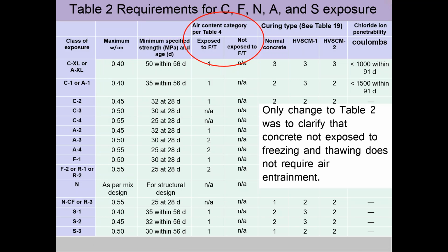Okay. One other change, the only change to Table 2, which is the exposure class table, is this thing I've circled here to separate out whether concrete's going to be exposed to freezing or not. Because there were some concerns raised, especially with some of the higher strength levels, like the CXL, where you need 50 MPa, that if you didn't have freezing and thawing exposure, it was difficult in some cases to get 50 MPa or the required strengths with air. And there was no need for air because they were never going to see freezing and thawing